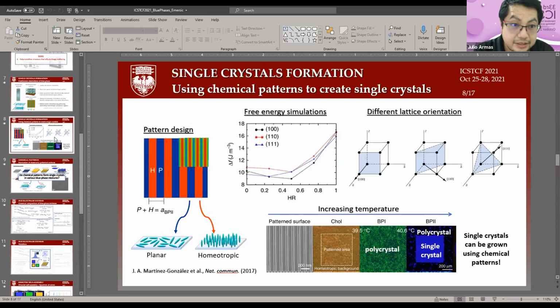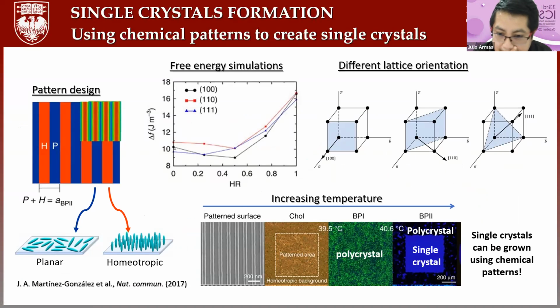Celsius. Okay, and the second one is, when you put the blue phase on the lithography, for example, if you want to apply this to make a display, I mean, to change quickly not the orientation of the molecules, but maybe the orientation of the lattice from one direction to another, because from the simulation you can find that the substrate induces a minimum in the global energy, and maybe it's hard for the system to move when applying an electric field or something like that. What is the possible application of the single crystal of blue phase? Because maybe for the display it's not a good one.